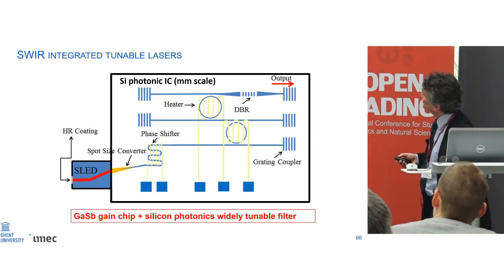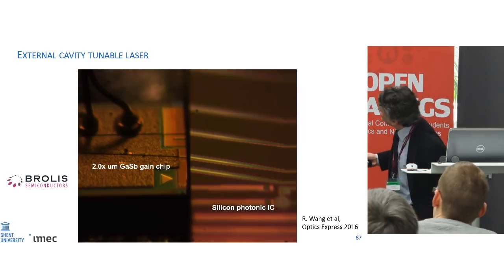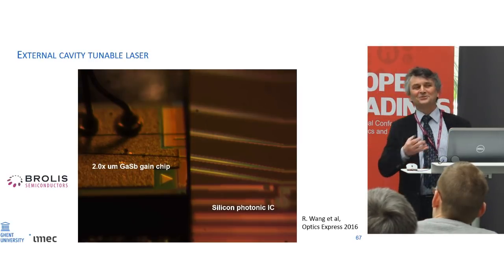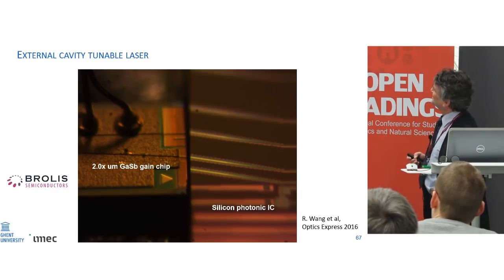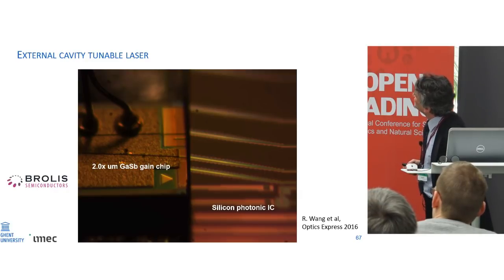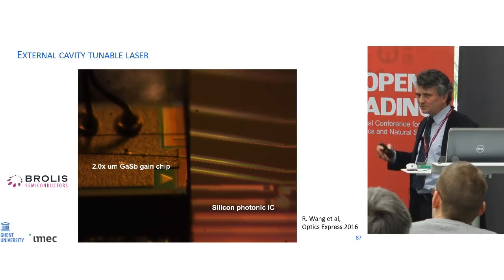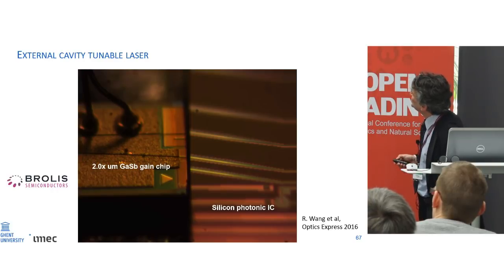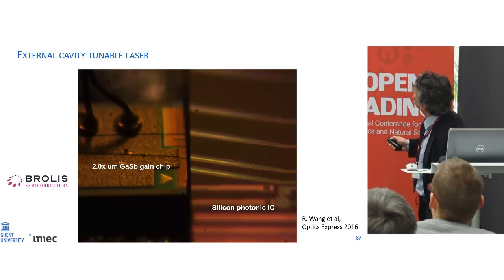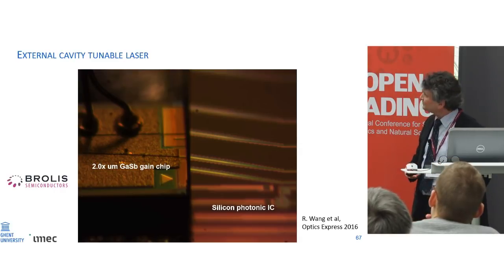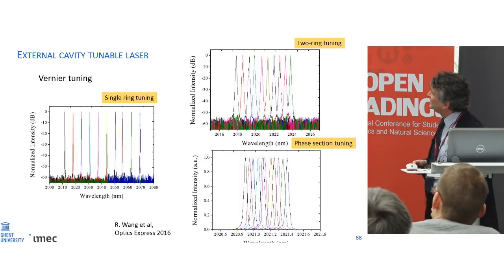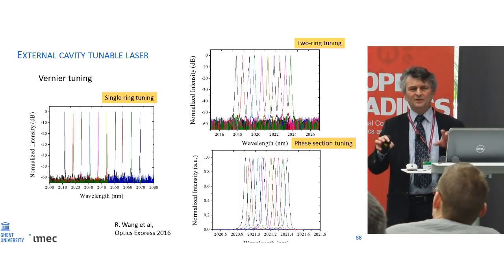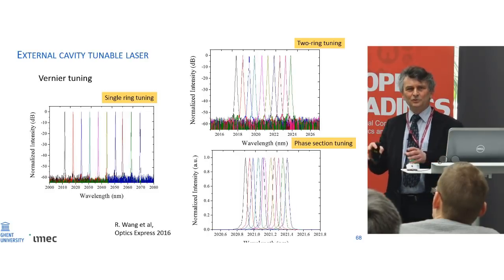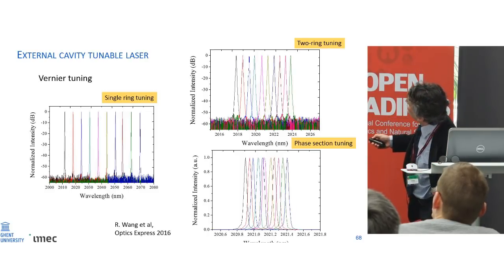This is what we did, and actually we did it here. Here you see a picture. Here you see the III-V chip. Actually, this was a chip from our good friends here in Vilnius from Brolis. It was a gallium antimonide gain chip. So this operates in the 2.0x micron range. And here you see the start of the silicon chip, but the silicon chip is actually much larger. And it works beautifully. In this case, we have three heating elements. And with three heating elements, we can do coarse tuning and fine tuning and ultra fine tuning. And that's what you see here.